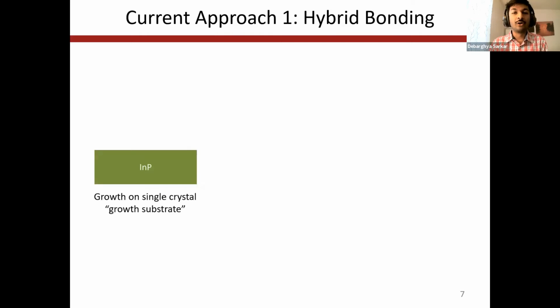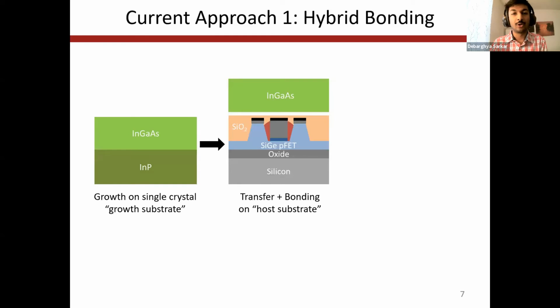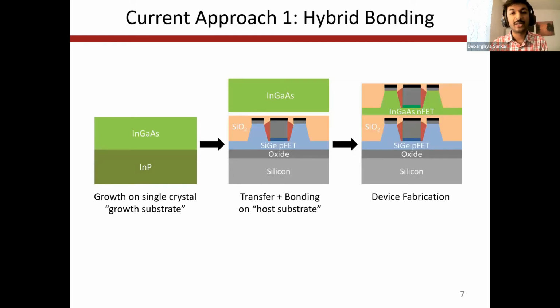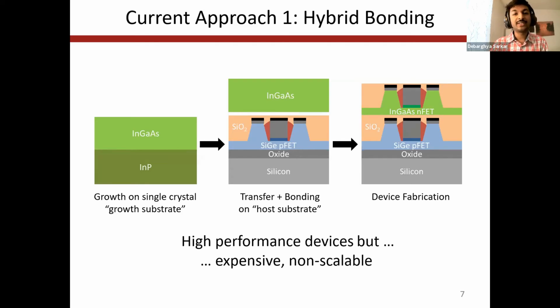Now, the most popular current approach for 3D integrated circuits today is called hybrid bonding. In this method, materials are first grown on a single crystal growth substrate, and then this grown material is transferred to a host substrate to which it is bonded, and finally, devices are fabricated from it. Using this method, very high performance devices have been demonstrated, but at a very high cost, mainly arising from the expensive single crystal growth substrate and the non-scalability between the growth substrate and the host substrate.